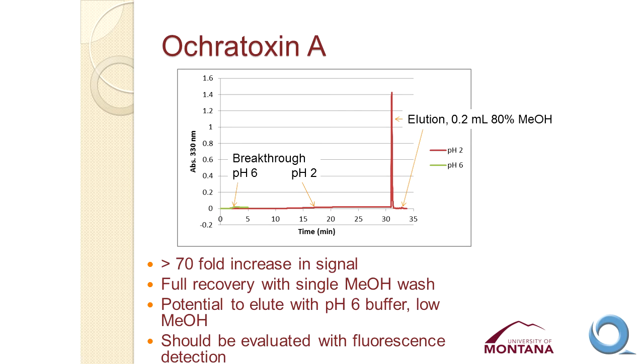All right, and then to carry that a little bit further, there's a lot here, but the green trace is the trace where we had pH 6, so no retention, and the scale is much different here, so we can barely see the increase in the signal for the compound coming through. The red trace is one of the traces I showed you before at pH 2, and so you see for a period of time out to 10, 15 minutes before you start to actually see that signal rise due to the breakthrough of that compound.